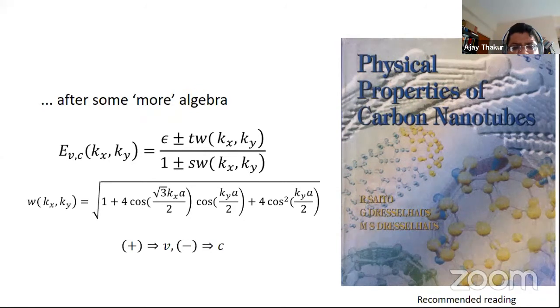In particular, after a little algebra, one can show that this energy dispersion would be given by this function, where t is the hopping parameter. So basically, this is how easily an electron can jump from one site to another, and which electron is jumping? In this arrangement of carbon atoms, carbons are connected to 3 other carbons via sp2 bonding, and then there is an extra electron, which is free to move up above, and that is available for carrying the current, right? In this particular case, the subscripts V and C stand for the valence and conduction band.